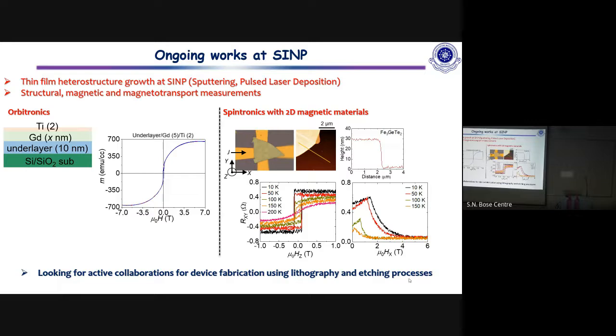And this is another result that is currently under review. We are working with a very well known 2D ferromagnet, iron germanium telluride. Over the last 2 years we were working on the bulk, doping it, but then we decided to make devices out of it. We found that in the bulk, this material has a very interesting ground state, which hosts topologically protected spin textures called skyrmions.